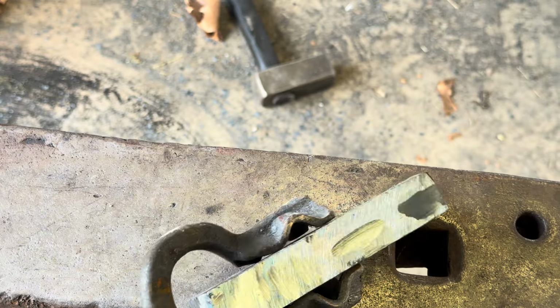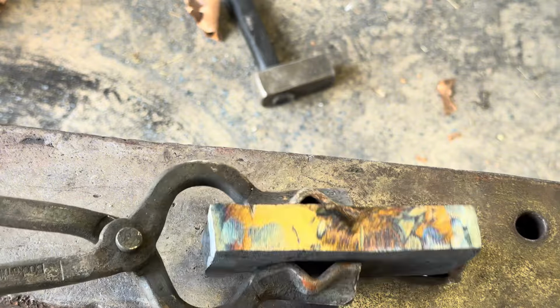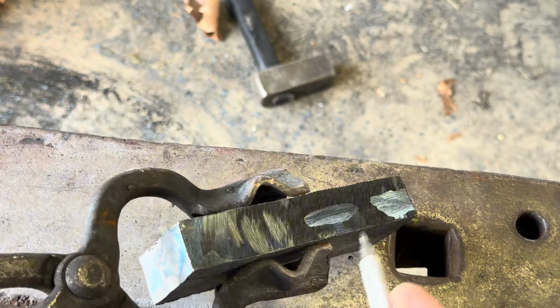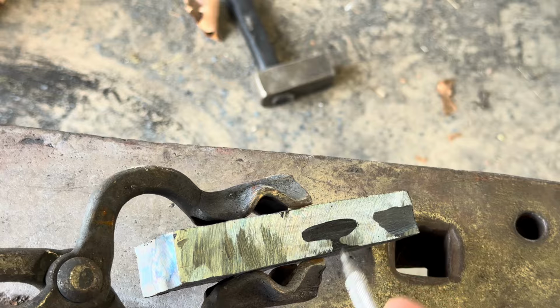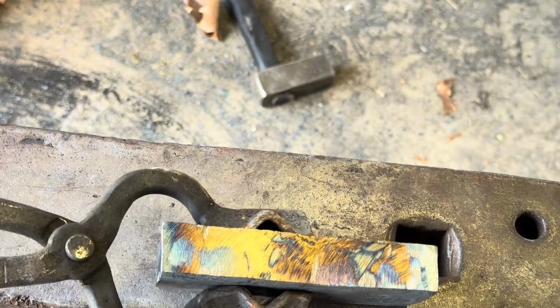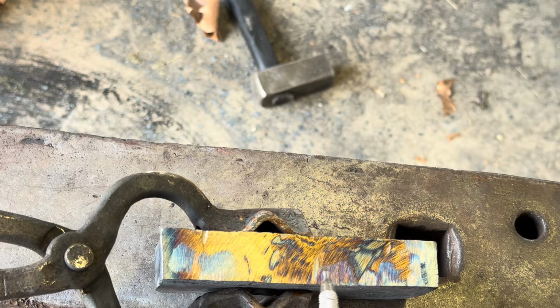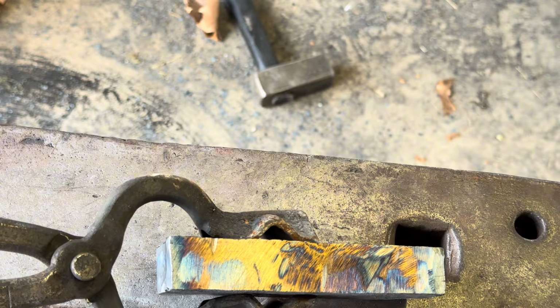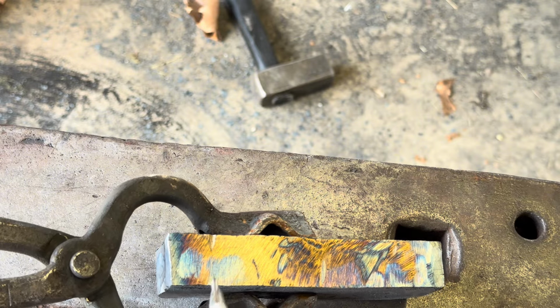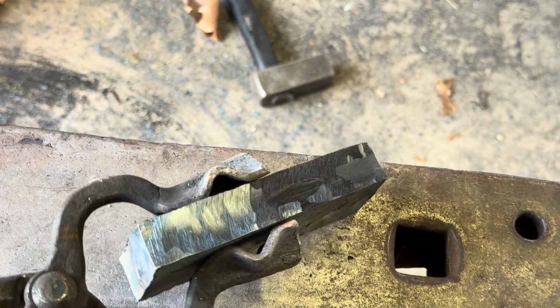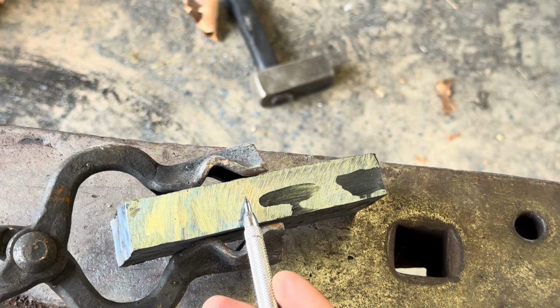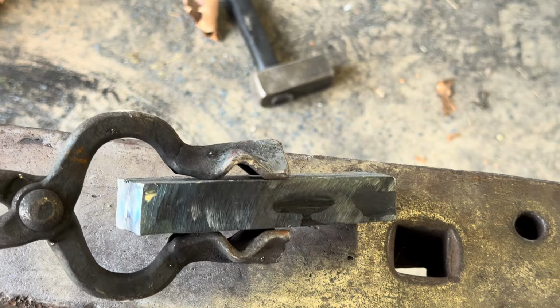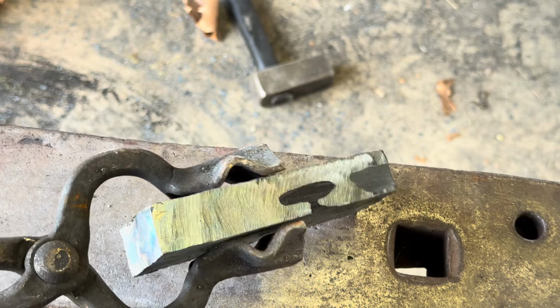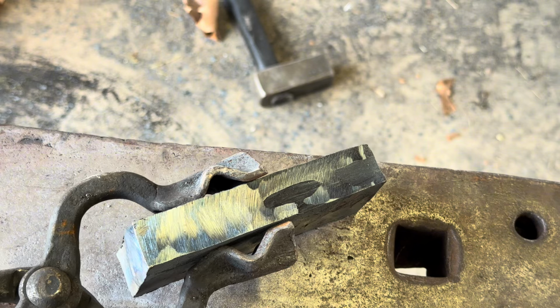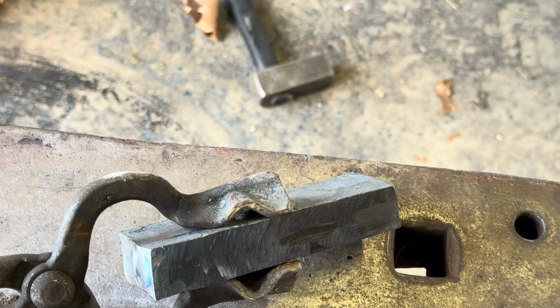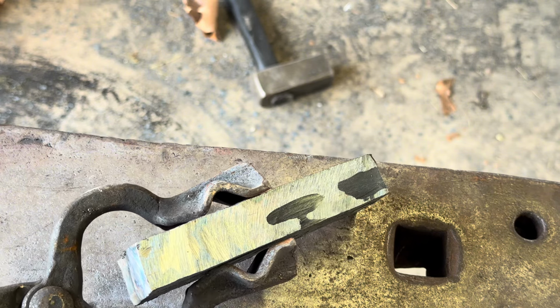However, I did find a few deeper inclusions. One right here, and then not as deep there. I was able to grind them most of the way out, this one here. There's a few minor ones, like there and on this side, there and there. But I think those are just on the surface, not very deep, and I can get that stuck back together with some flux and some careful hammering.